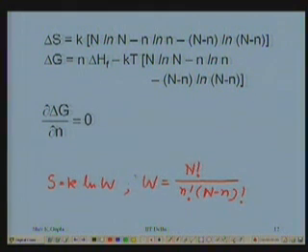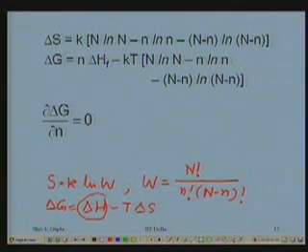All right. Then I can write down the free energy delta G, which is delta H minus T delta S. Delta S I already got. So, delta H is what I have to work out. Delta HF is the enthalpy of formation of one vacancy. Since I have n vacancies, it is n into delta H sub F minus delta S into T, so kT within bracket, N log N minus n log n minus (N minus n) log (N minus n). If it is reducing or making it a minimum for a certain number, I can find that out by differentiating this with respect to n and putting the derivative to 0.